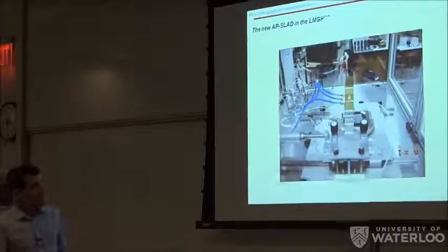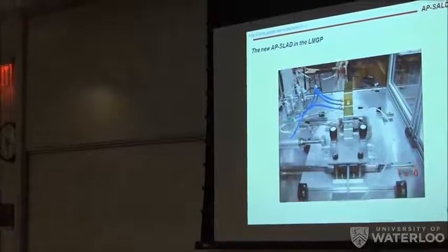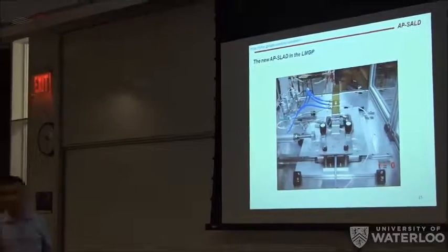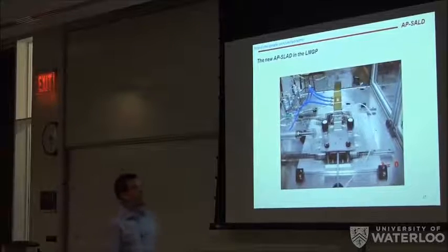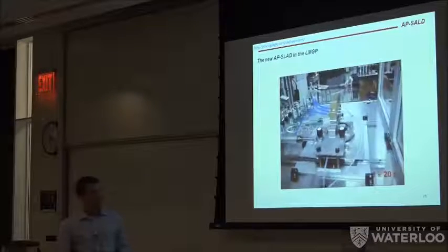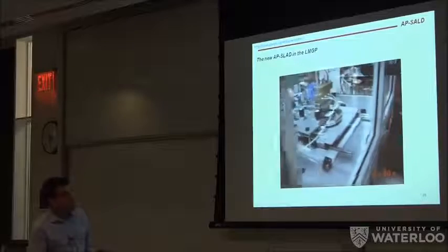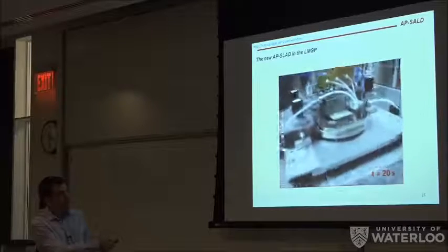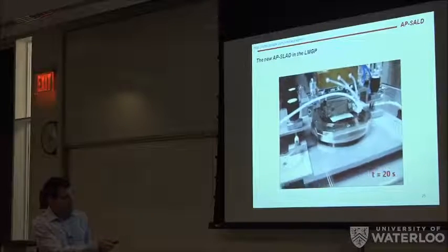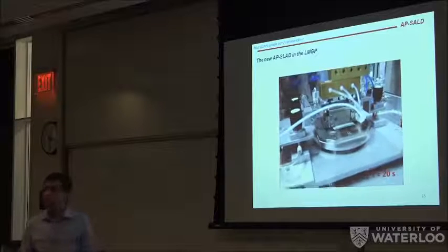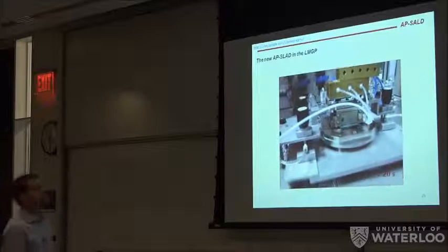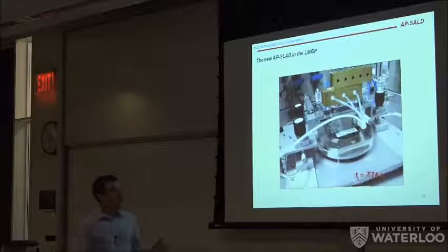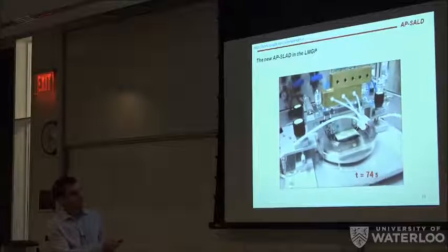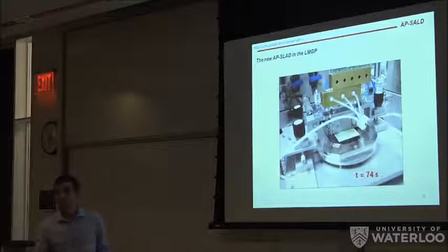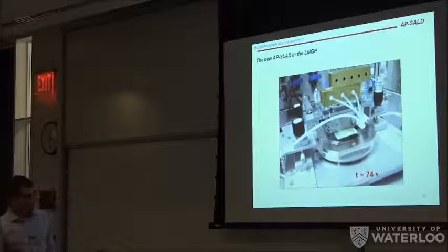And that's a video where you can see how we actually grow a film. At time 0, we start scanning the sample under the head. We're growing zinc oxide, and you will see that just after 20 seconds, hopefully you manage to see, we have already a film appearing there. You see that we are really close to the substrate to ensure that the gases are kept apart from each other. After a little over a minute, you see the film, which is 30 nanometers, maybe 40, keeps growing.